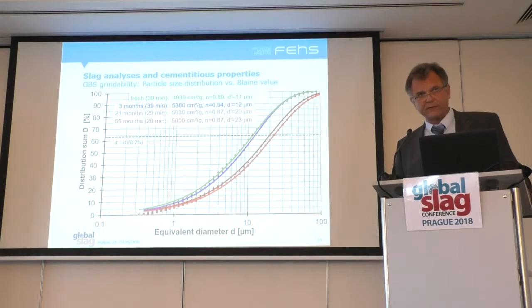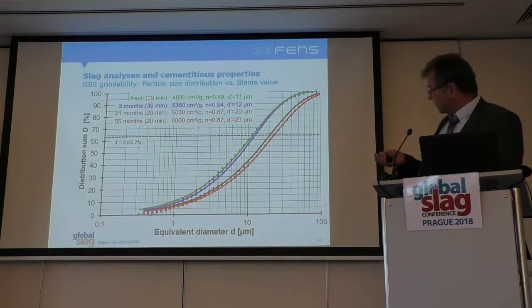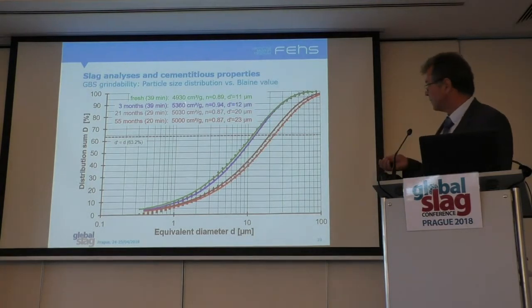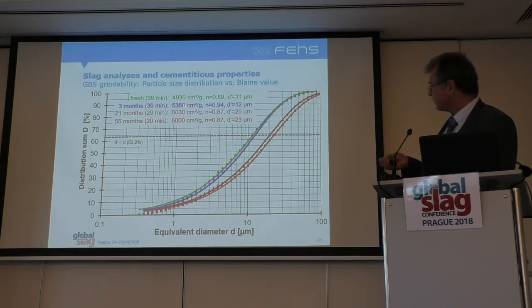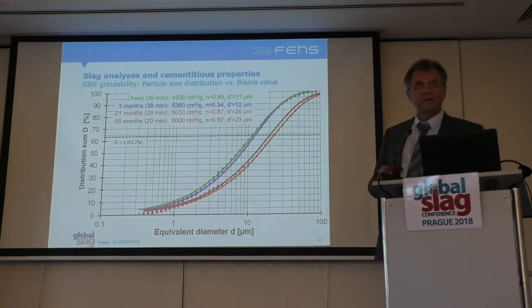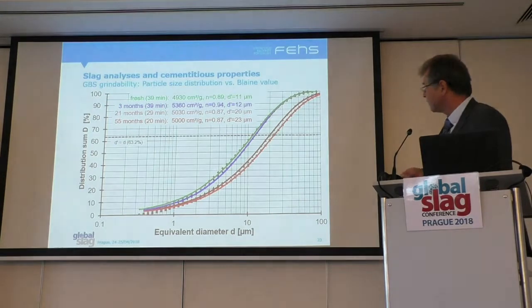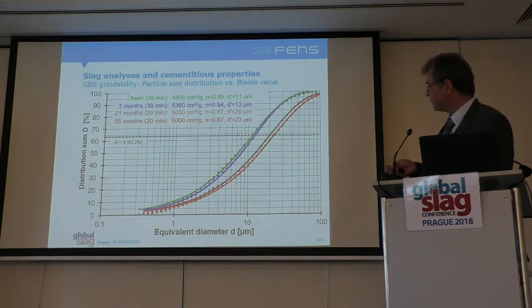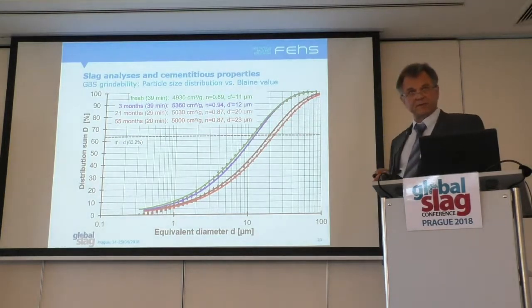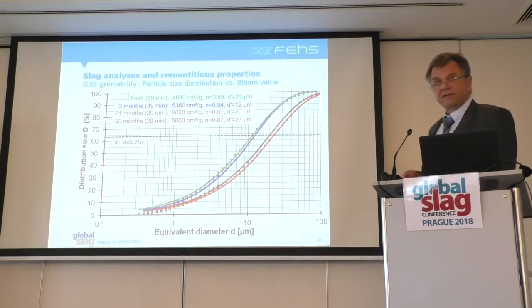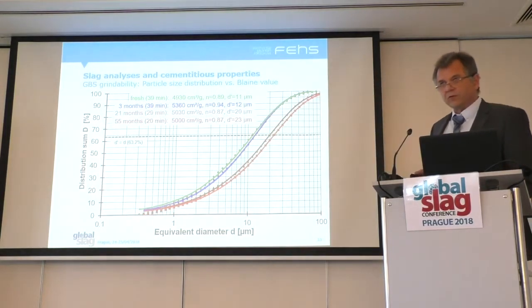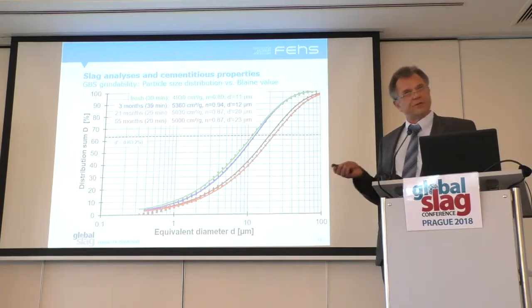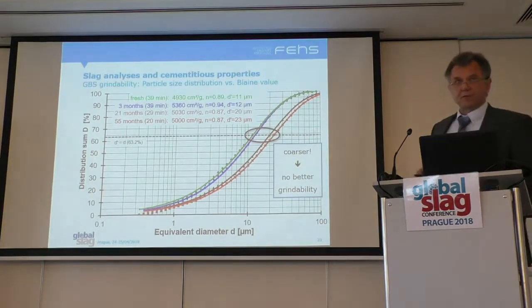But looking at the real fineness, at the particle size distribution, we see that that is the starting point, that is the fresh slag after the Zeisel test. Around 5000 Blaine. After 3 months, after the same test, we have 400 Blaine more. But we have at least a very similar particle size distribution. At the end of the storage, we got the same 5000 Blaine already after 20 minutes grinding instead of 39 minutes, which means half. But the material is much coarser. So according to Blaine, you save a lot of grinding energy. But according to fineness, you have a coarser material. And therefore, there is no better grindability.